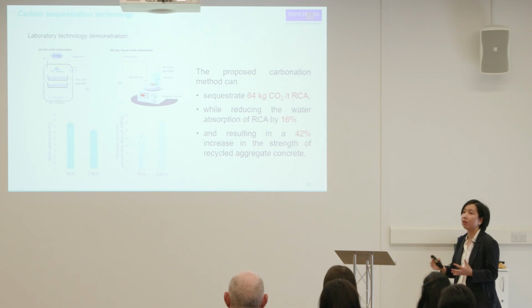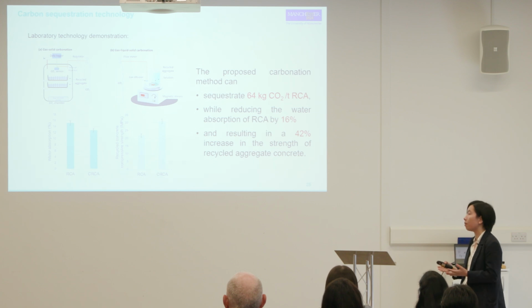The laboratory tests are already investigating and validating these two potential methods for carbonation technology. One is under the dry condition, the other one is under wet condition. And the benefits of carbonation on recycled aggregates have been validated as well. From the tests, we found that about 64 kilograms of carbon dioxide can be permanently sequestrated by 1 ton of recycled aggregates. The water absorption of the recycled aggregates can be reduced by 16%. The strength of the recycled aggregate concrete can be increased by 42%.